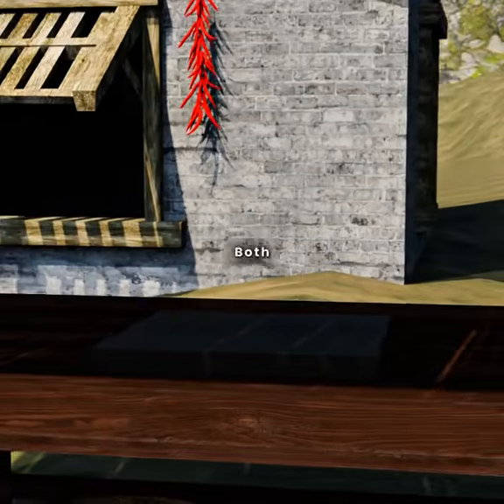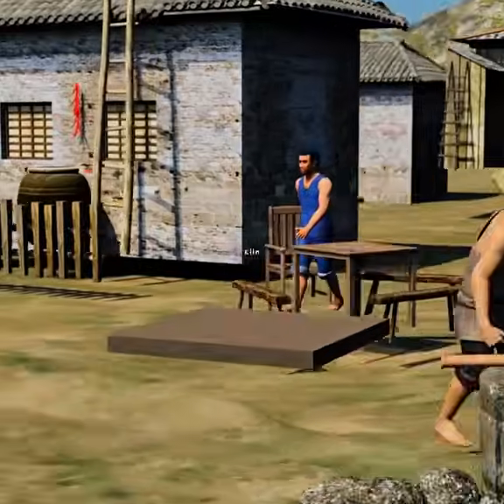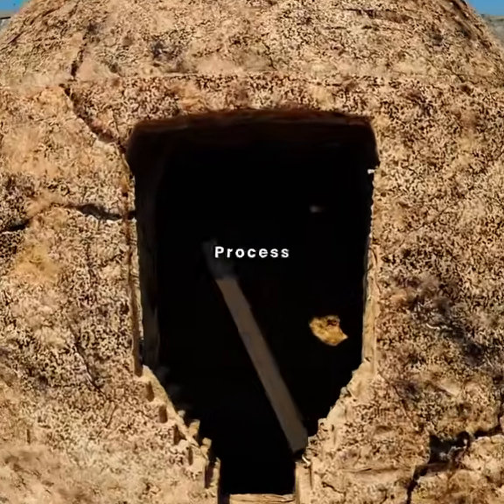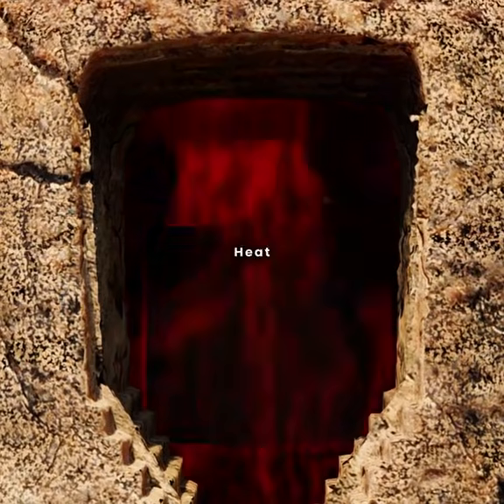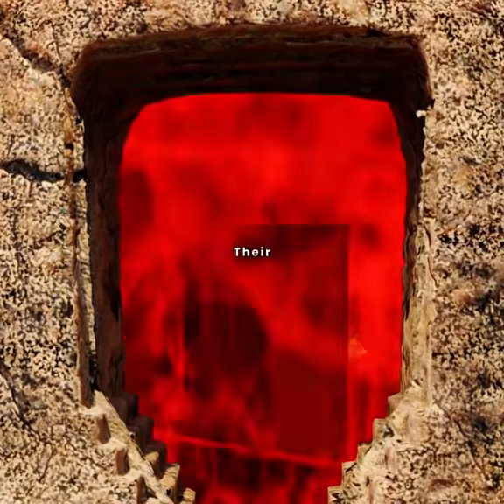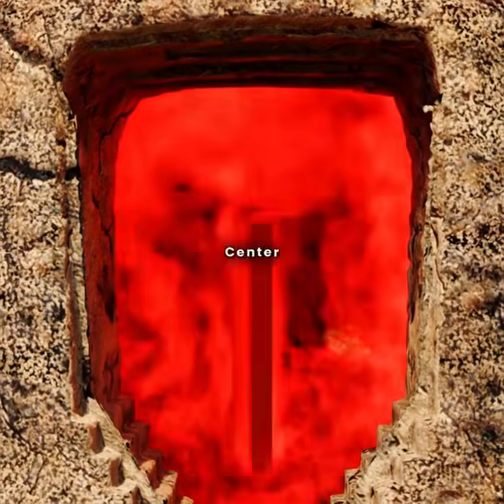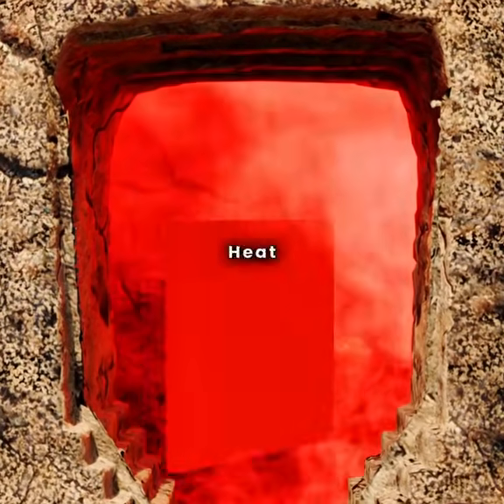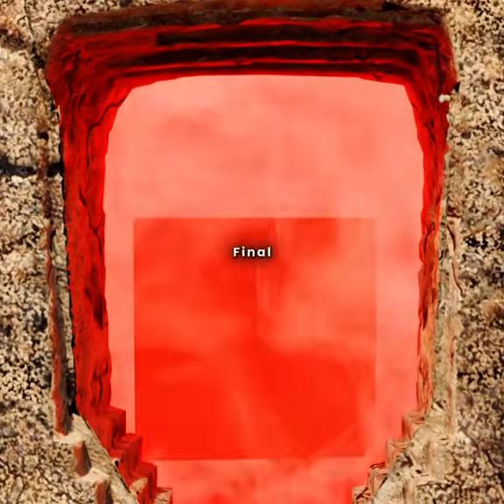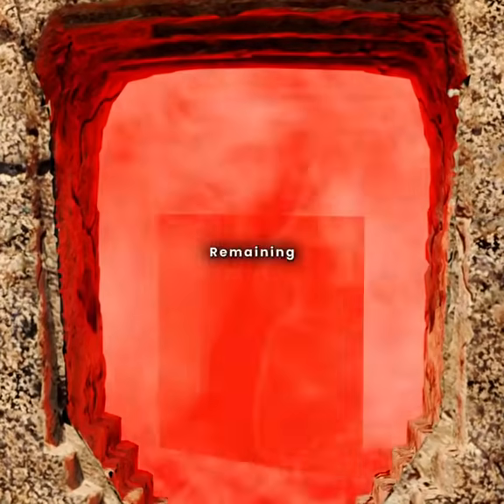The molded bricks were then shade-dried indoors, protected from both wind and sunlight, for a full 12 months to prevent cracking. Finally, they entered the kiln for an extraordinary 4-month firing process. 1 month of gentle, low heat to slowly remove moisture and stabilize their shape. 1 month of medium heat to sinter and harden the body. 1 month of high heat to increase density. 1 final month of intense heat to eliminate any remaining impurities.